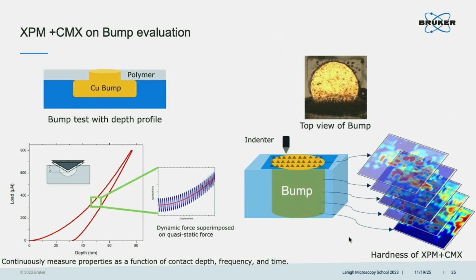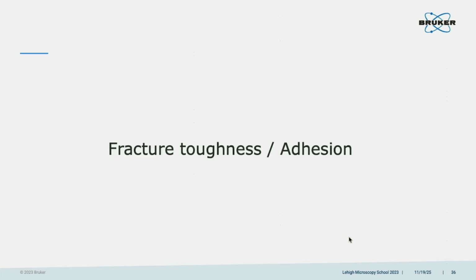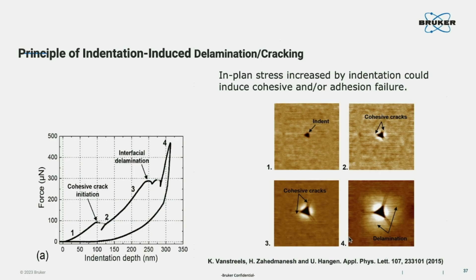So we have high-speed mapping. We have the depth profile. Then with the nano indenter we can do mapping at different depths. It's like a CT; we call it mechanical CT, right? All the mapping is at different depths. If your sample has a depth gradient, this is a very useful technique for understanding how the mechanical properties map at different depths. And for fracture toughness, we have in situ SPM.